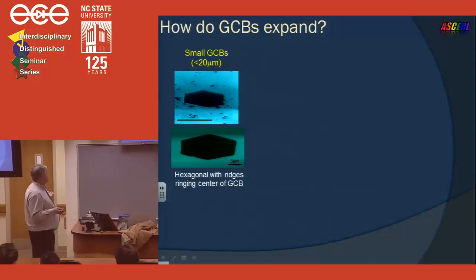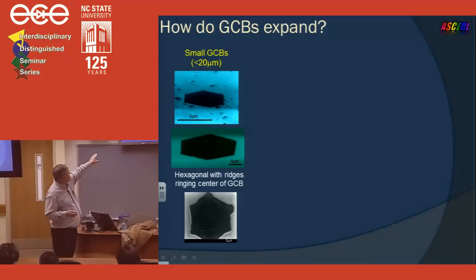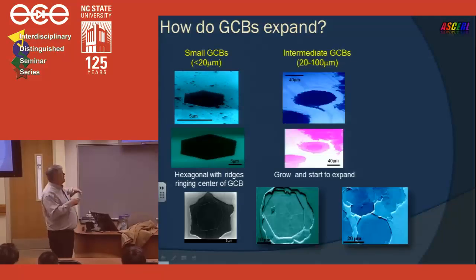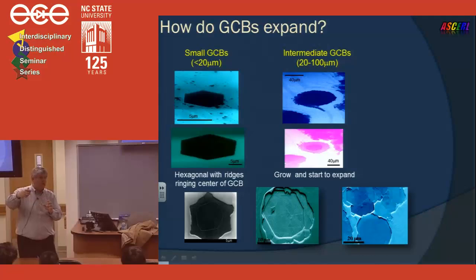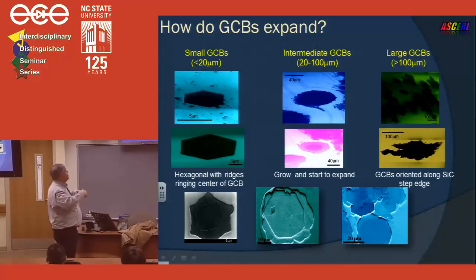Here's some of the small ones, and they have this nice hexagonal symmetry, which is very beautiful. And in some cases, you see some with ridges. And then we look to the larger ones, and they start getting more irregular in shape. As you can see in the bottom pictures, sometimes they start colliding with other graphene-covered basins that are being formed, and the walls between them eventually erode away because of the sublimation process. And then you get to even larger graphene-covered basins. And these take on extremely irregular shapes.